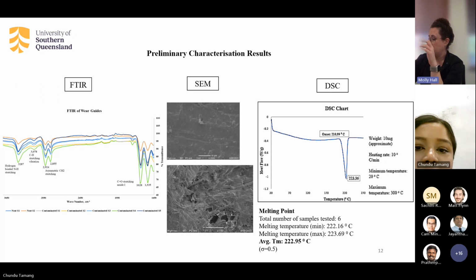So firstly, for the FTIR, 5 different contaminated samples and 2 neat samples were tested and compared to determine the unknown materials and the surface contamination. All the peak wave numbers of the IR spectra represented the major functional groups constituting polyamide 6 and were identical for all the samples, including both neat and contaminated, as per the assignment of the IR bands reported previously in literature. Secondly, for the scanning electron microscopy test, the neat guide samples were seen to possess a continuous, flat, smooth, and clean surface with fewer irregularities, which indicated homogeneous and good quality morphological properties.